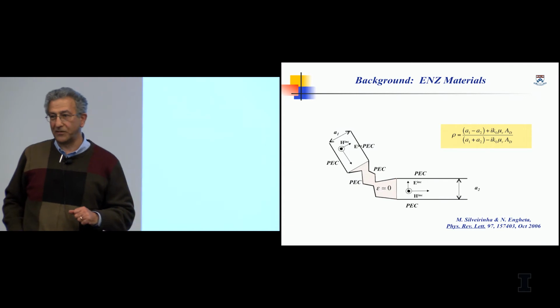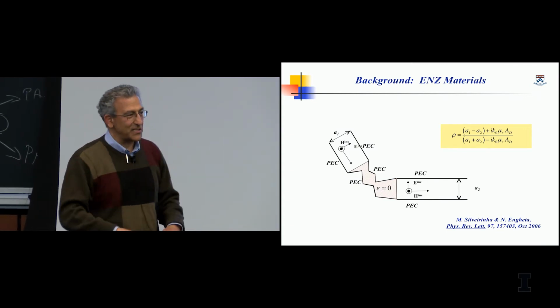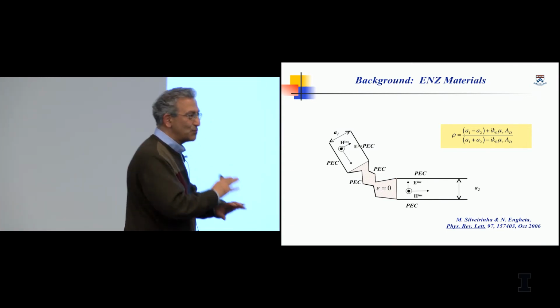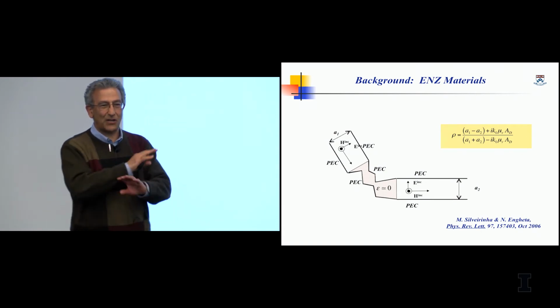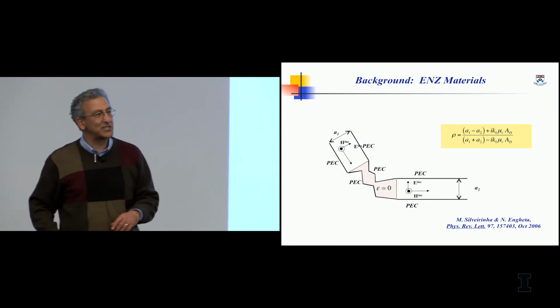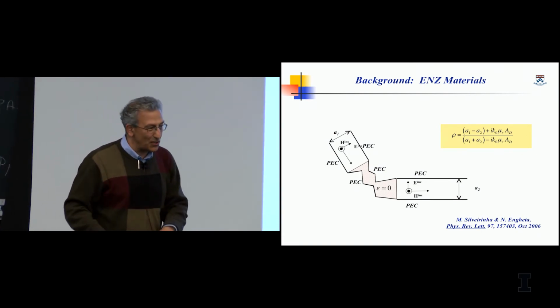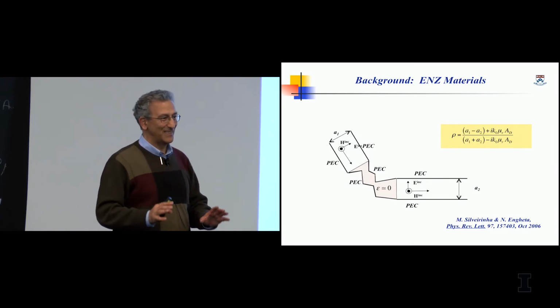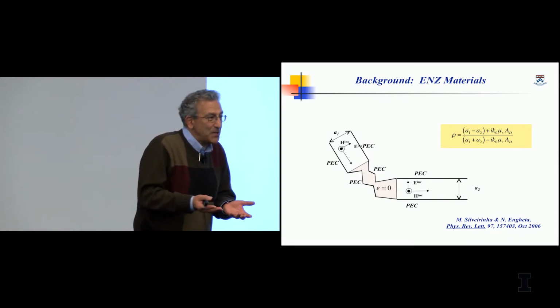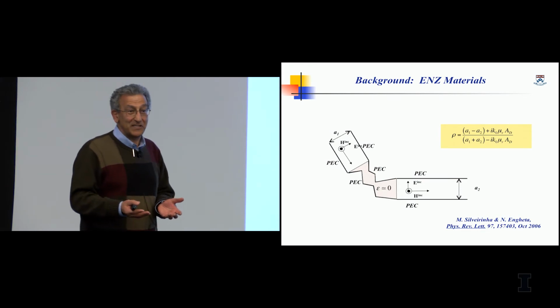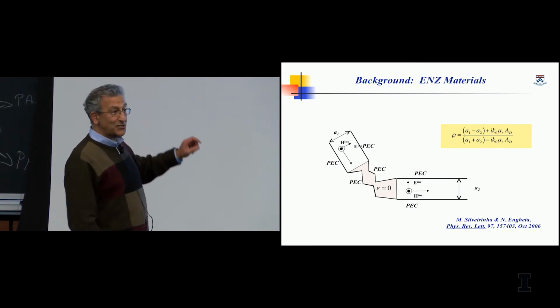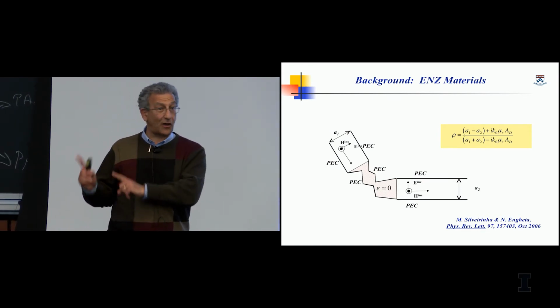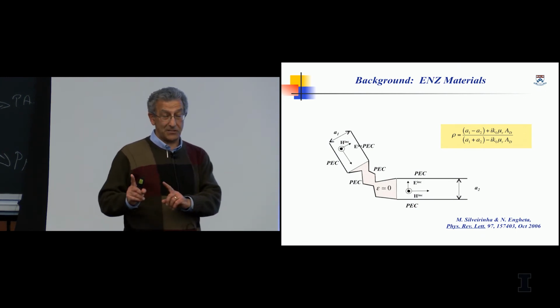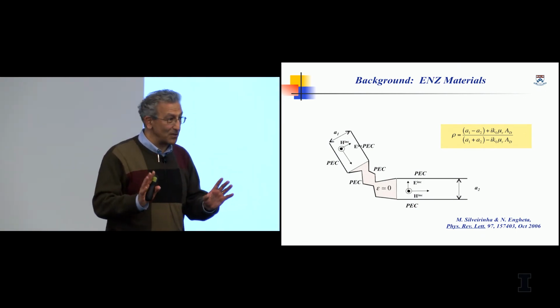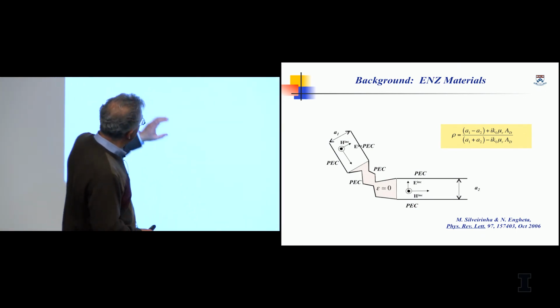At first, we didn't believe this. We tested. We examined. Everything was consistent. Maxwell's equation satisfied everything. Then we decided to do the simulation. Everything worked out. Then we decided to do experiment. Everything worked out. And indeed, actually, this became an interesting area in metamaterial, that this ENZ structure can give us very interesting, unique tunneling that is very different than Fabry-Perot tunneling. That's very different. It's specifically for this ENZ.